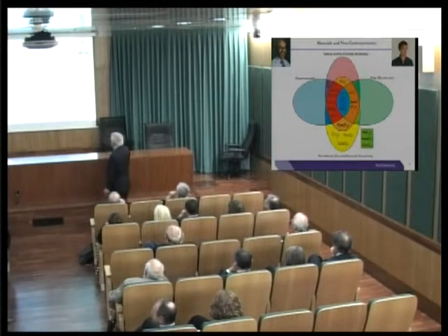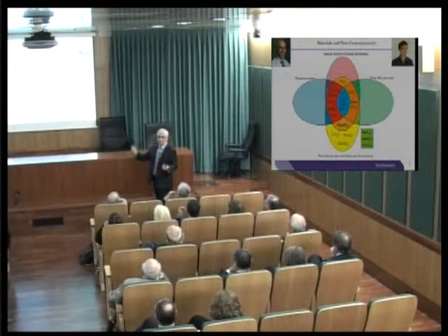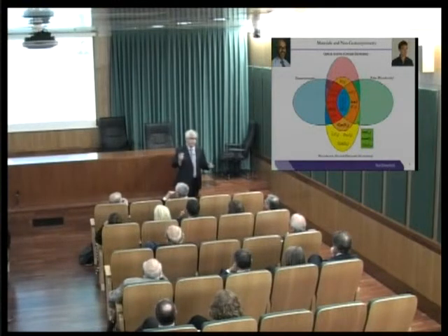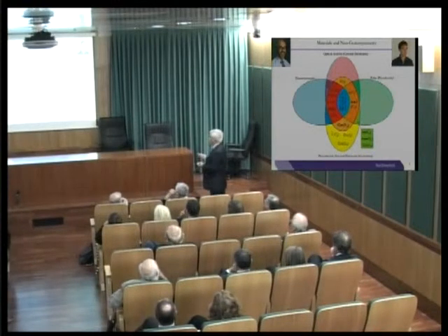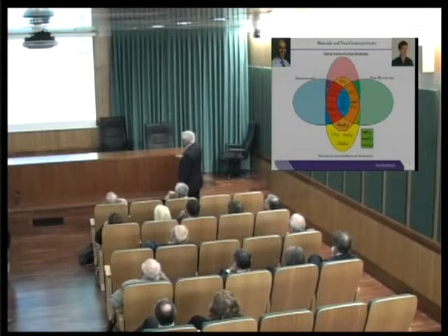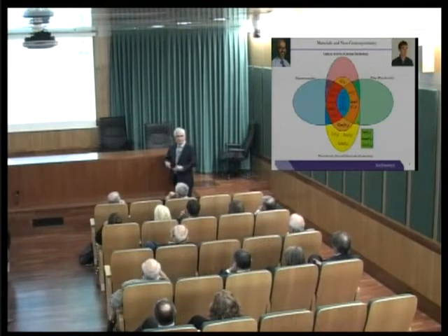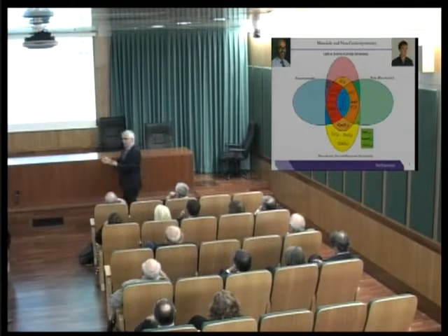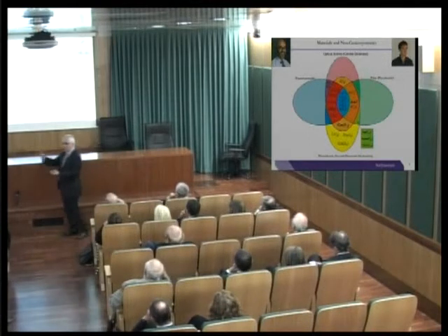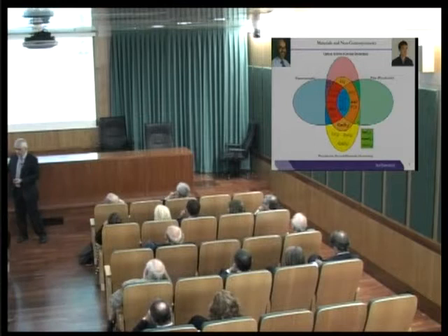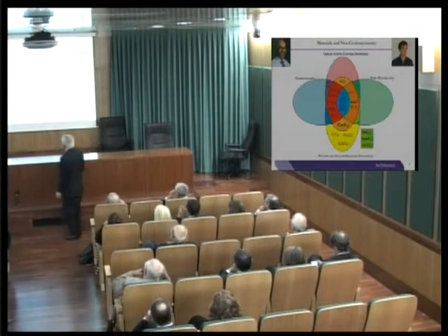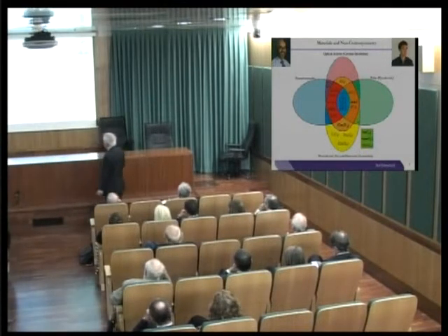But we've grouped them. These are the ones that have some dipole associated with them because they lack inversion symmetry, the so-called polar groups. The ones in this ellipse are the ones that are piezoelectric, and there's the possibility then that you can have second harmonic generation. If you shine light in at one energy, it can be frequency doubled or quadrupled or even sextupled, right? So this is NLO, nonlinear optical behavior.